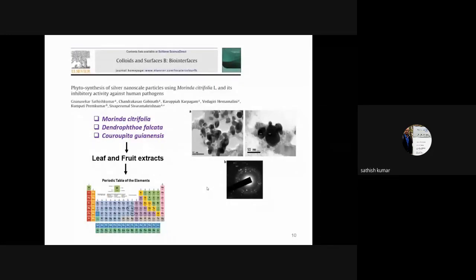The extracted leaf components were used with silver nitrate as the precursor, and we obtained nanoparticles with a size range between 10 and 60 nanometers. Here you can see the polydispersed nanoparticles, and the particles are quite aggregated. In plant-mediated synthesis, we cannot predict the exact active compound that plays a crucial role in synthesis, reduction, and stabilization, because the plant extract obviously has a mixture of compounds. So we cannot say which particular compound is involved. Also, we cannot predict the mechanism of reduction.